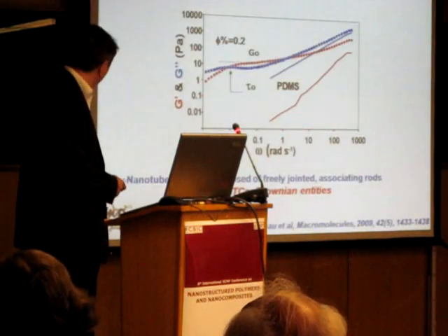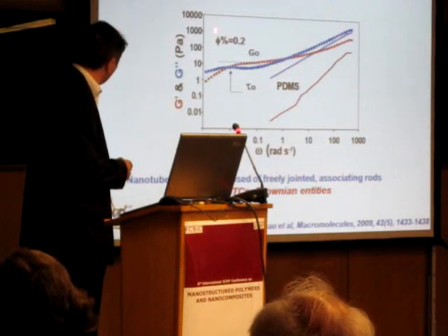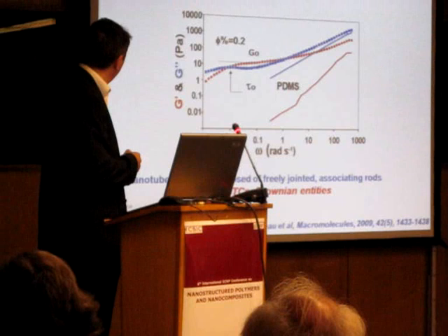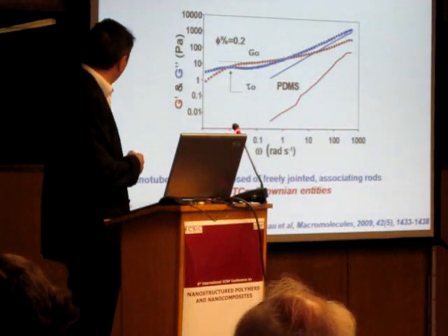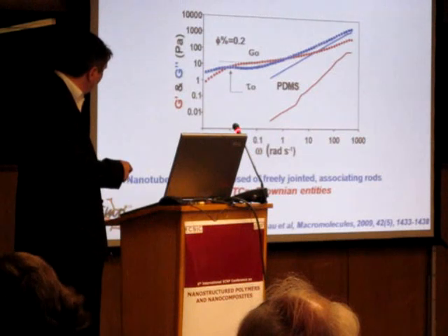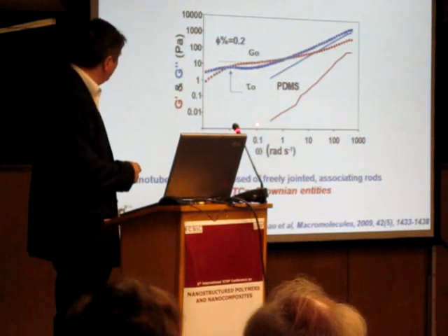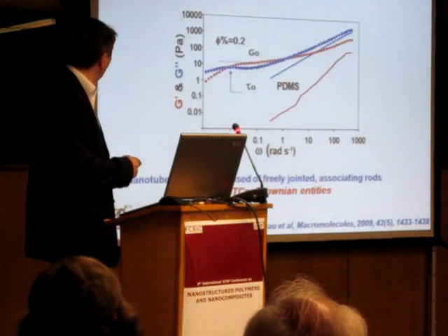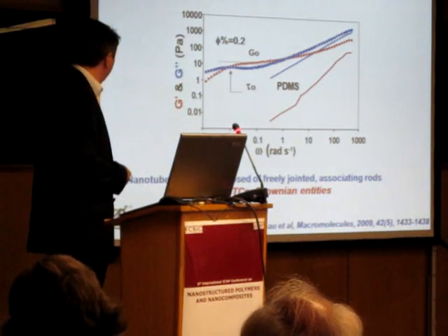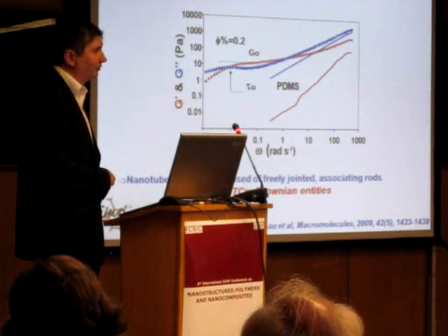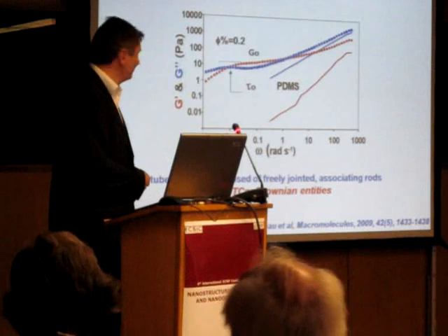So the first result is about the viscosity of this suspension. There is important data in this slide. First, the rest time. The rest time is about 48 hours. And the frequency here is from 0.01 to 1000. So this kind of experiment takes about 68 hours. So you need about more than 60 hours to do the experiment. So fortunately, you are not obliged to be in front of the rheometer. You can put the sample on Friday and on Monday you have the results.